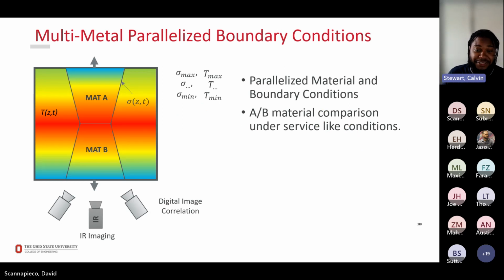Now, the final crazy idea is, well, what if we just wrap everything together? If we have parallelized material, so we have a multi-material print, gradient material, we have a gradient temperature field, and we have a non-uniform geometry, so we get gradient stress. Well, such a sample could be a great sample for A-B material comparison, where maybe we have two candidate materials we want to put in service. We don't know which to go with. Well, we could design this very specialized test to help us make a decision on which material is best for our specific performance requirements.